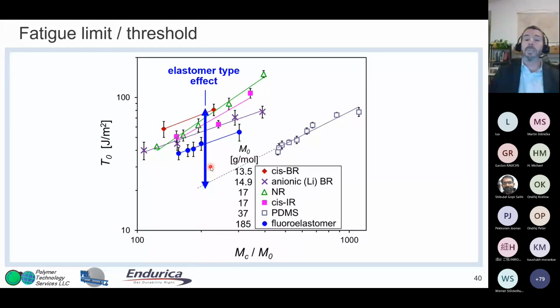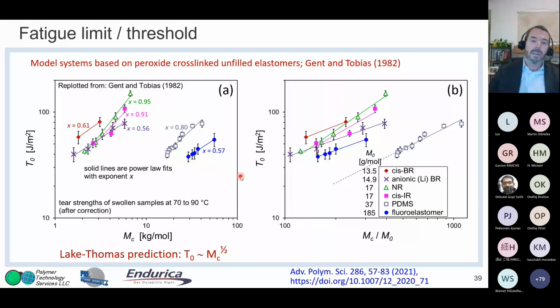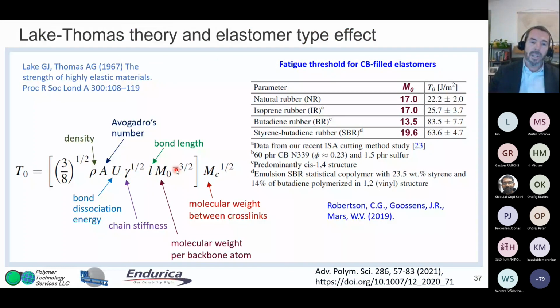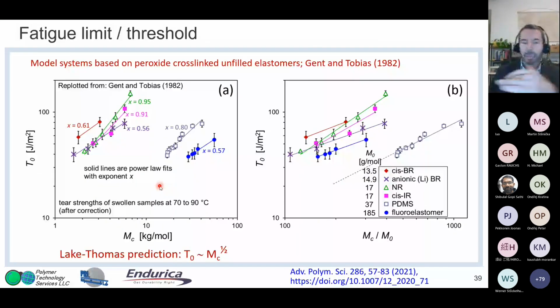These materials are intrinsically weak because they have fat polymer chains, right? This dependence on M0 is smaller is better. So that means a lighter backbone means a skinnier polymer chain. And so it basically means more polymer chains have to be broken per area, and therefore that leads to a higher fatigue threshold. And so you see something like polydimethylsiloxane and fluoroelastomers have really high M0s, and they have very low fatigue thresholds. So the elastomer type effect can be very nicely rationalized based on this molecular theory.